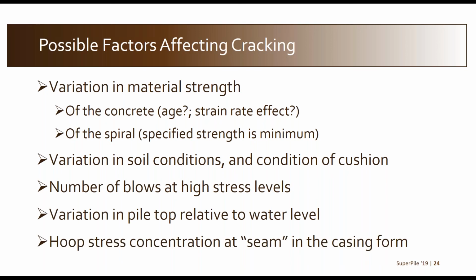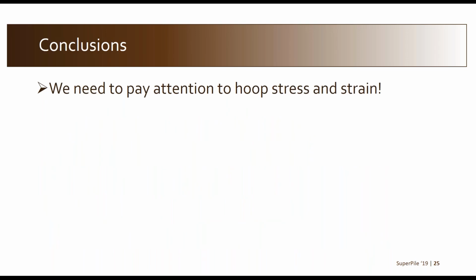Another thing that's interesting to ponder is that these precast piles have a seam from the way they're constructed in the casting yard, and there's likely a stress concentration at the top at least because of a slight eccentricity when you're driving the piles. Everything's never going to be perfectly aligned. So maybe it's kind of a worst case scenario where that seam aligns with the maximum stress due to some eccentricity, and those are the piles that cracked, and in other cases, things were in a more favorable orientation to avoid cracking. So all these factors potentially explain why cracking did not occur everywhere.